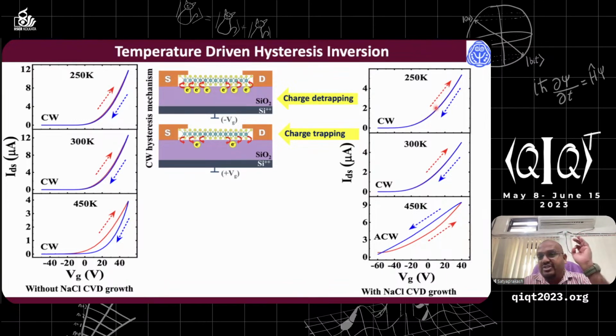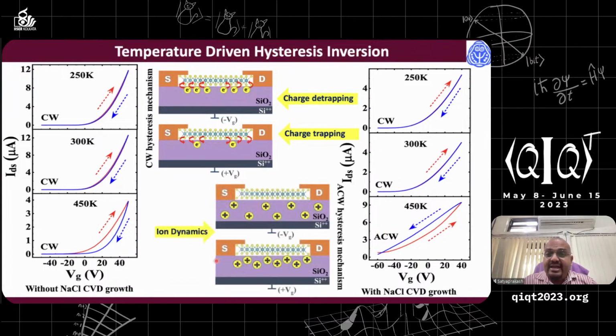That means initially at low temperature it was clockwise, then at high temperature it suddenly becomes anti-clockwise, which is something very interesting. And this can be explained in terms of ion dynamics. What is different between this and this is that when you grow this material in a sodium chloride environment, the sodium goes into the silicon dioxide, and thereby this sodium activates or becomes more mobile at high temperature, and it contributes to the conducting channel, and thereby you see a drastic change in the hysteresis. It becomes a reverse hysteresis, or anti-clockwise. You go like this, then come like this.